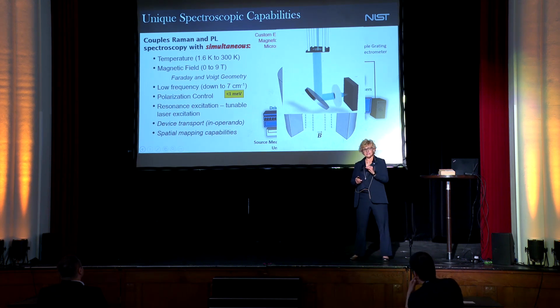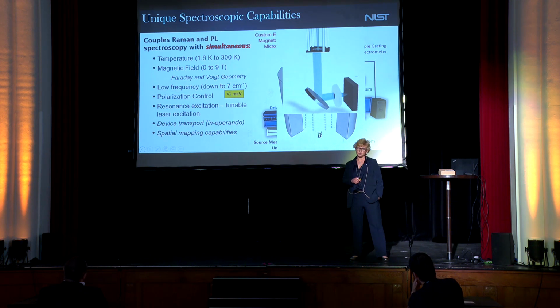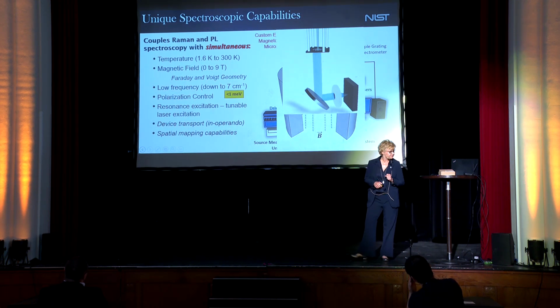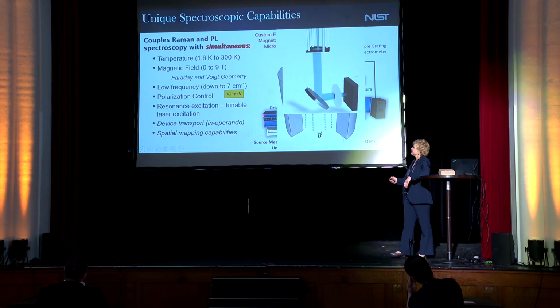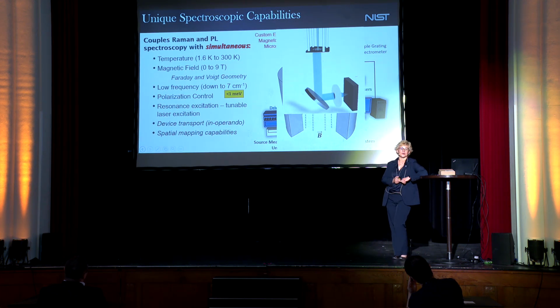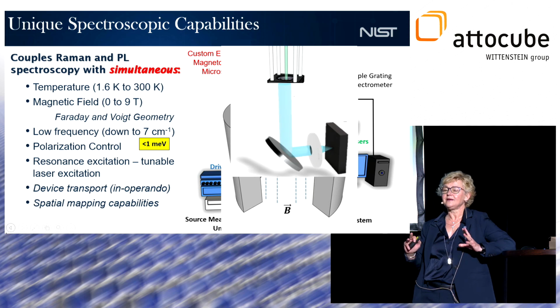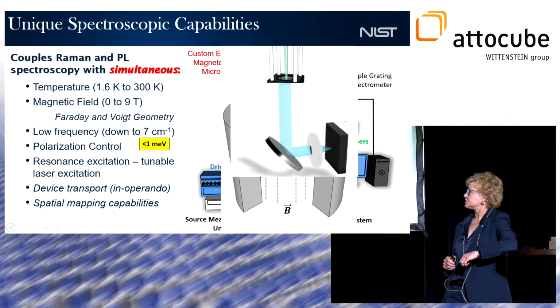The other unique piece is we have tunable lasers throughout the visible. We're using CW lasers, again, very common for Raman. We built up this capability back in our nanotube days, just to age myself. Having tunable visible lasers was very important. So we can more or less span from about 400 nanometers to 800 nanometers excitation.